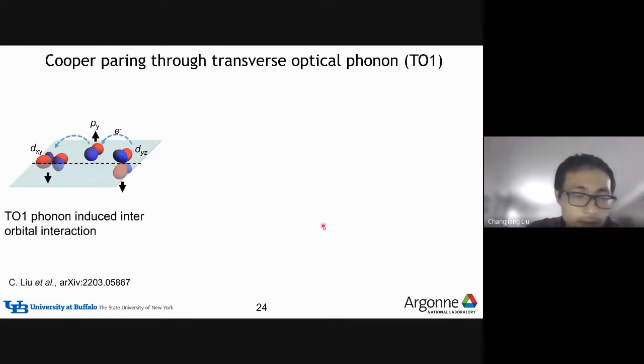So later on, my collaborators did the theoretical part of this work. With our collaborators, we found that the transverse optical mode, or TO1 phonon, could be responsible for producing this striking interfacial superconductivity. Just to remind you, the transverse optical phonon involves, for example, the oxygen p orbital and the d orbital on the B site. Once you have a transverse phonon movement, there will be an induced hopping.